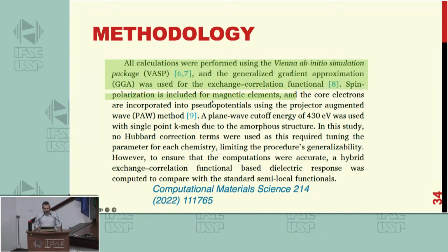They use spin polarization. If you put magnetic atoms, you see that I only mentioned silicon, oxygen, sodium, aluminum. However, if you put transition metals into your simulation, you need to take special care. You do not run the simulation as for silicon oxide. You have to turn on some flags in the code, that is spin polarization, okay? So here they use the PAW method, that approximation for pseudopotentials. Plane waves is some other technicality related to how reliable your calculation is. K-points, oh, this is pretty interesting.